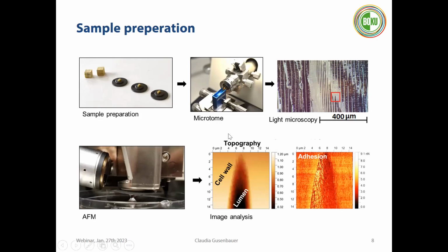And we can distinguish between the cellular layers and the lumens. And we also analyze a lot the adhesion forces. So the adhesion force is the force that we calculate out of the tip movement when the tip is not in contact mode, but in a tapping mode. And the tip is always touching our sample with really low forces. And from the force that we need to move the tip back to the previous position after it touched the cell wall, we can calculate the adhesion force. I will go into detail on this later on, but in this mapping mode, we get topography information, and we also get adhesion mapping.